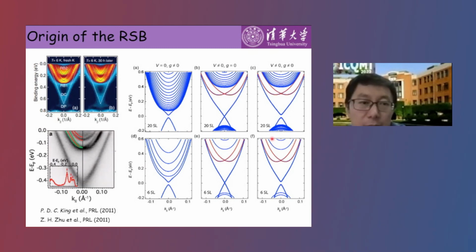The Rashba split band observed in the films and the bulk samples resembles that in bismuth selenide after surface doping, which is related to the quantum well state formed after surface doping. Based on the 4-band model for topological insulators, we simulated the band structure of manganese bismuth telluride slabs. The surface doping mainly induces surface potential. Without this surface potential, the antiferromagnetic term opens a gap in the surface Dirac cone near the gamma point.